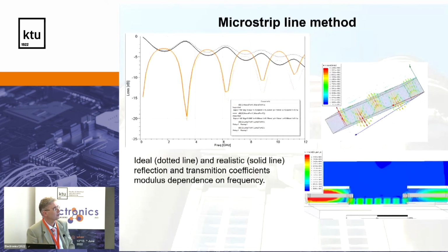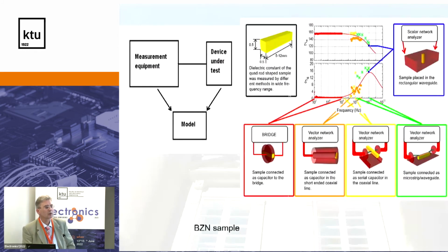And another thing which I would like to show shortly, due to time limits, is the strip line, when we have an electromagnetic wave propagating. Here is our sample, a coaxial line, and this method goes up to 12 gigahertz, quite well. So, an example, BZN, bismuth zinc niobate ceramics, measured by different methods. Simple capacitor, red, frequency range; coaxial line, yellow, sample connected between two coaxial lines, sorry, yellow, that's brown, and strip line, green, and we are getting the whole dielectric dispersion of this material. So it's not so simple, not so easy, but possible to extract.